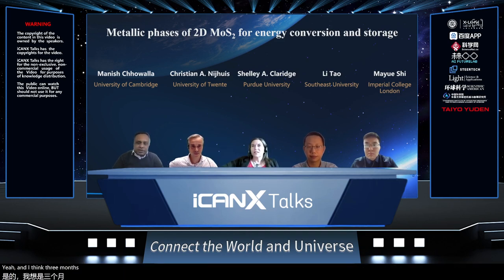Yeah, no, thanks very much. That's a great question. So, we've been studying defects in MoS2 from both the electronic point of view, where we're trying to minimize sulfur vacancies and really decrease the carrier concentration to get to an intrinsic level, and from a catalysis point of view, and even from a battery's point of view, having these sulfur vacancies is really useful as active sites, but also as adsorption sites for the sulfur, ensuring that the polysulfide remains on the electrode host rather than dissolving into the electrolyte. Every time we've looked at MoS2, whether it's mechanically exfoliated, chemically exfoliated, or CVD grown, we see heaps of sulfur vacancies. They're present, and they're usually isolated.